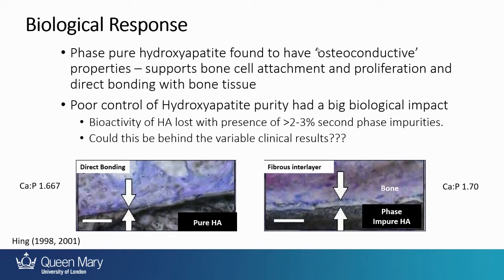So with pure hydroxyapatite, you've got direct bone bonding. With the impure hydroxyapatite, you've got this fibrous interlayer formed. So it was no longer bioactive. And that explains a lot of the variability people were getting in materials from first generation when they didn't understand that you needed to be this controlled with the phase purity. So a manufacturer might have had a plus or minus 5% tolerance on impurities, and that would have been enough to stop the material from being reproducibly bioactive in the clinical situation.